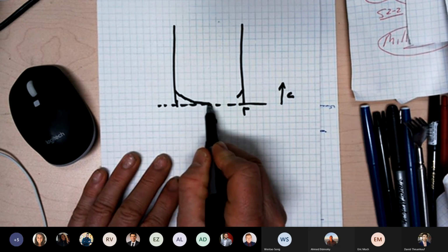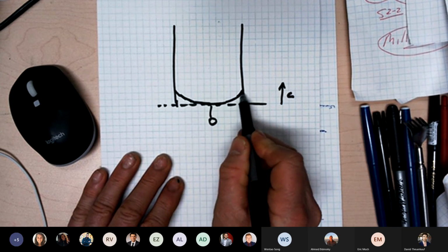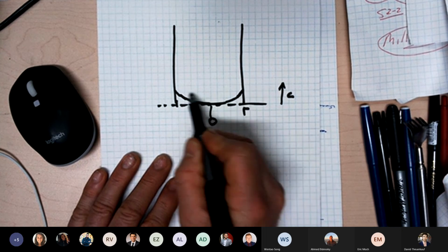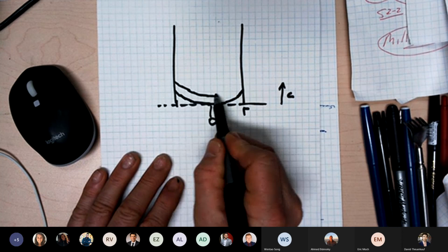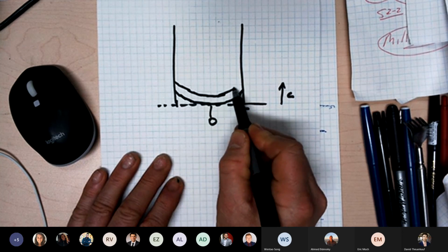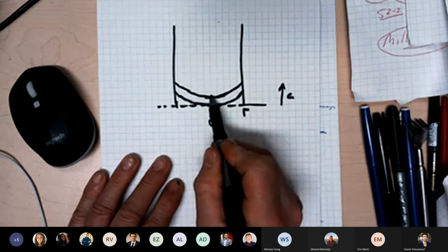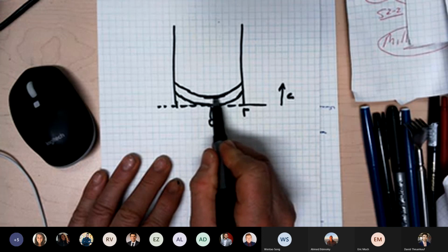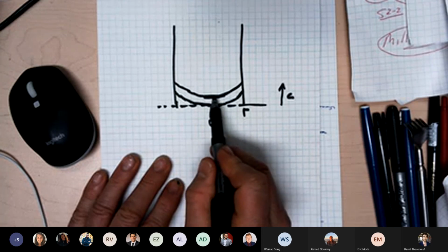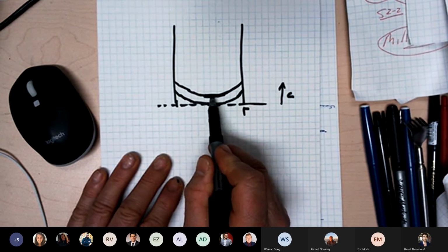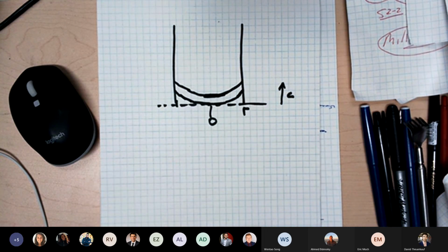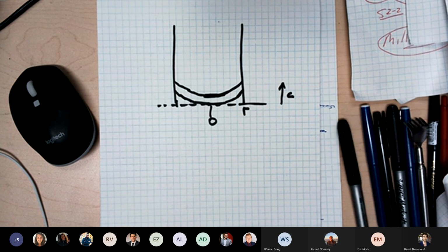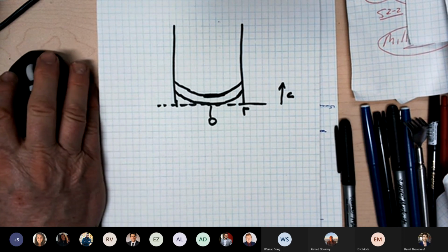It'll go down, it's still 0 in the middle. But it has to show symmetry. It's a symmetric particle, so as you put more lithium in, you're always at 0 at a place where it's minimum concentration. So the derivative of concentration with respect to position is 0 because of this symmetry here. Okay? So that's what that other condition means.